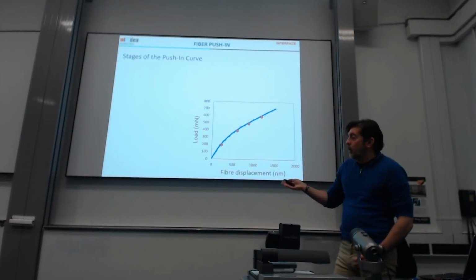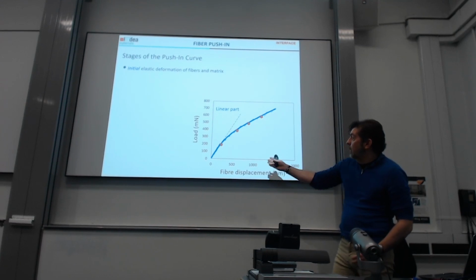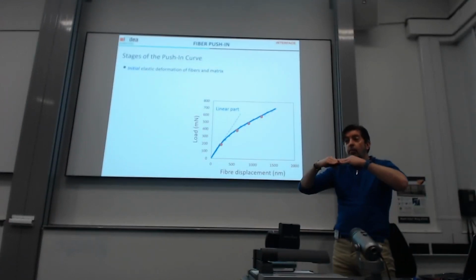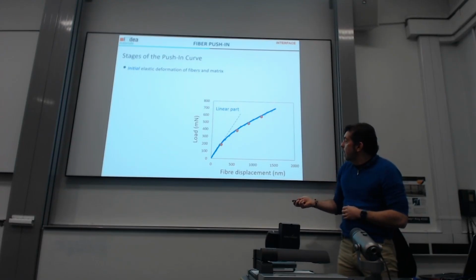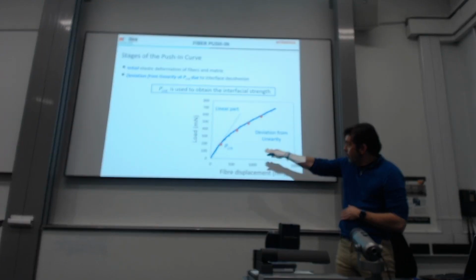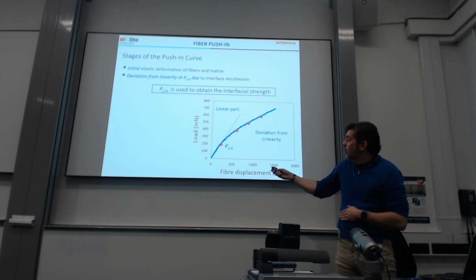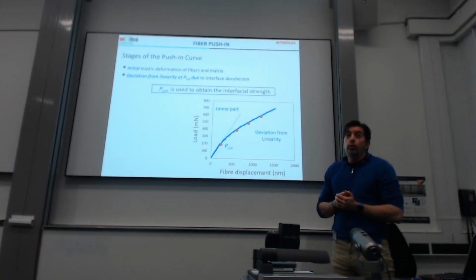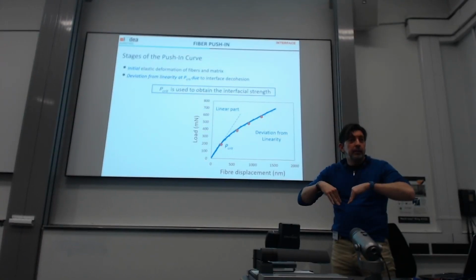When you get the pushing curve, of course, you have a linear part due to the elastic deformation of the fiber and the surrounding environment. And this ends in the non-linear part, where we have a deviation from linearity, and we have some sort of critical load that marks the debonding of the interface.